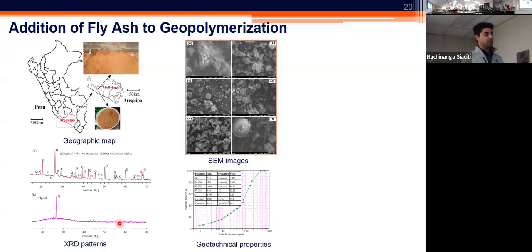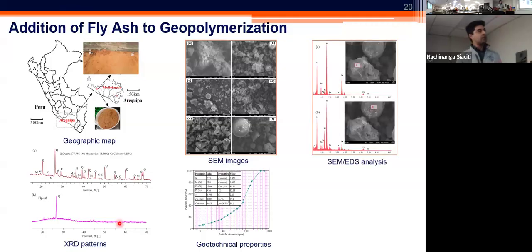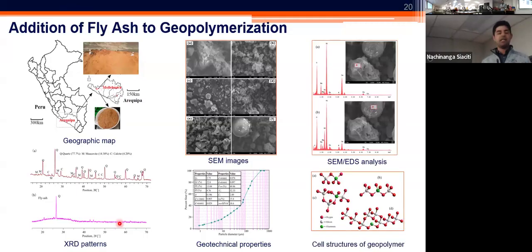So we did that. We evaluated the mixture of the tailings and the fly ash in different percentages of addition of fly ash. And I think we went up to 20% addition of fly ash while still maintaining that high percentage utilization rate of the mine tailings. So again, with the 20% fly ash addition, we had 80% of the tailings used in that production process. Looking at the SEM evaluation of the tailings and the fly ash, we recognize that the fly ash has a fairly higher amount of the aluminum and silicon that can help to facilitate a better connection and development of the network of the polymerization. So we also have this understanding that the silicon to aluminum ratio would be a key determining factor that can be favorably adjusted by the addition of the fly ash.